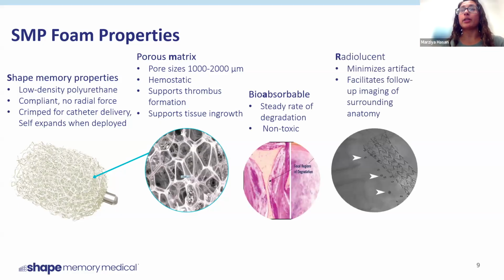Our material is also radiolucent, meaning that it is not visible under X-ray, and that's why we have the marker bands that I showed you in some of the previous slides. The marker band is the actual radiopaque component of the device, so that when the physicians are deploying these devices in the body, they know exactly where they are. The foam itself, however, is not radiopaque, but this is beneficial for us because it lets us image the surrounding anatomy without a lot of artifacts.